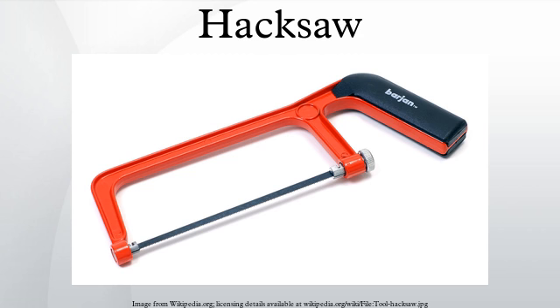The pitch of the teeth can be anywhere from 14 to 32 teeth per inch for a hand blade, with as few as 3 TPI for a large power hacksaw blade. The blade chosen is based on the thickness of the material being cut, with a minimum of 3 teeth in the material. As hacksaw teeth are so small, they are set in a wave set. As for other saws, they are set from side to side to provide a curve or clearance when sawing, but the set of a hacksaw changes gradually from tooth to tooth in a smooth curve, rather than alternate teeth set left and right. Hacksaw blades are normally quite brittle, so care needs to be taken to prevent brittle fracture of